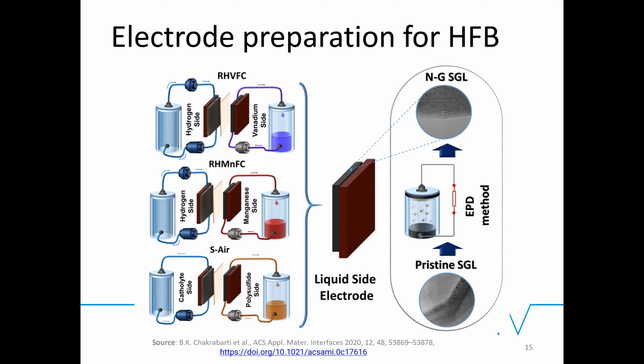So we thought, if we try a horizontal way, keeping the working electrode at the top, would that change the outcome? After a few trials and errors with deposition times of 10 minutes, half an hour, 1 hour, and applied voltages from 10 volts to 700 volts, we managed to get 300 volts for 30 minutes. We managed to get the reduced graphene oxide particles to stick onto the surface of the carbon paper, and we found good performance in the battery as well. When we made the same system with the nitrogen doped graphene, the same parameters also gave good performance.